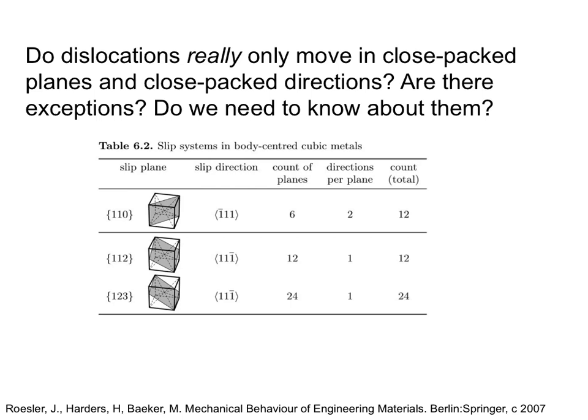We saw earlier in this video about what happens in HCP, and those are not all close packed planes, obviously, as well. In terms of do we need to know about them, I think that it's useful to know that there are different slip systems. We won't be solving problems where you need to identify these. One thing to note is that when dislocations move in close packed planes, it's a lot easier for them to move, and the stress that's needed is a lot lower.